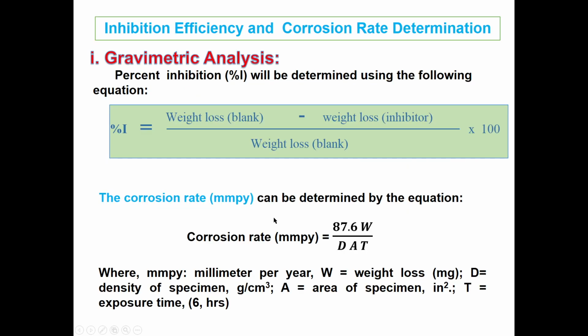In the gravimetric analysis, the percentage inhibition is calculated based on this relationship: the weight loss in the blank, that is, without inhibitor, minus the weight loss with the inhibitor, per unit weight loss in the blank. So this inhibition percentage we checked for different concentrations and different temperatures also. The corrosion rate is also calculated from this well-known formula in millimeter per year, where W is the weight loss, D is the density of the specimen, in our case the mild steel, A is the area of exposure of this sample, and T is the time of the exposure.